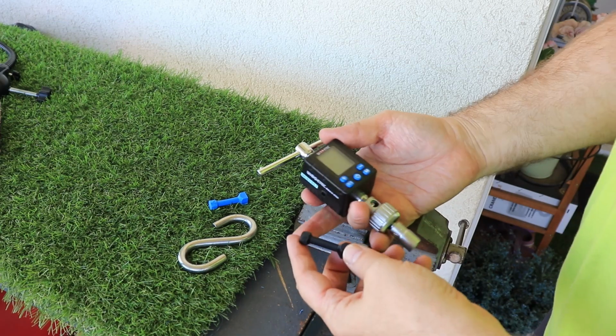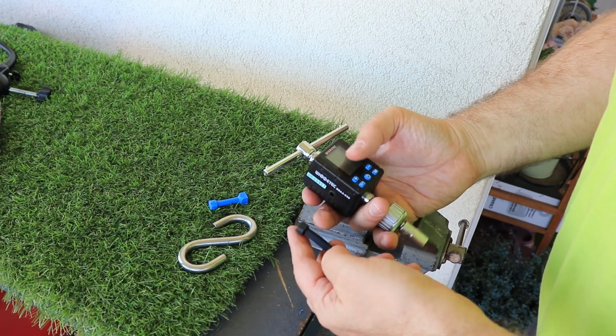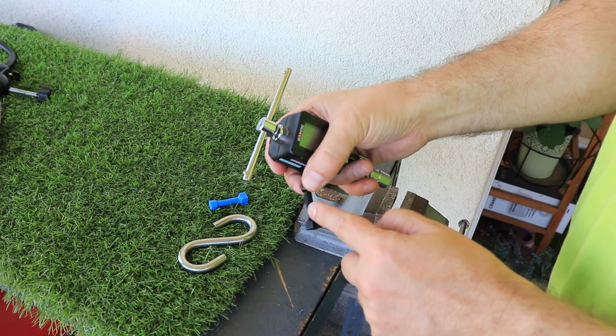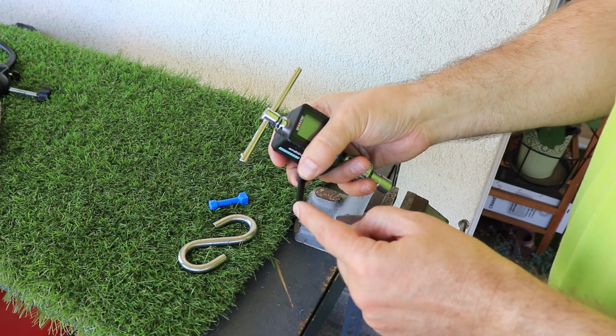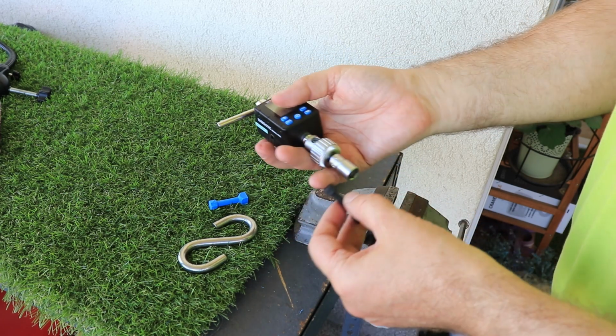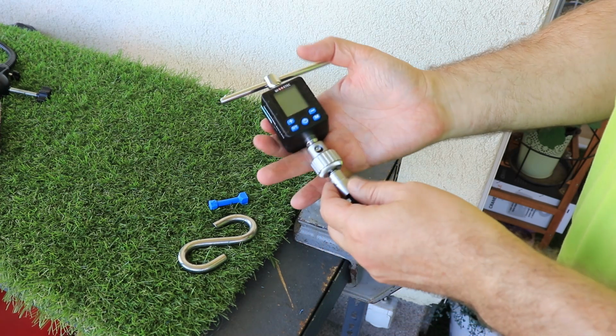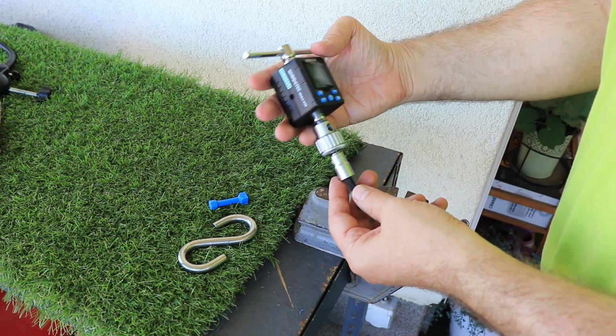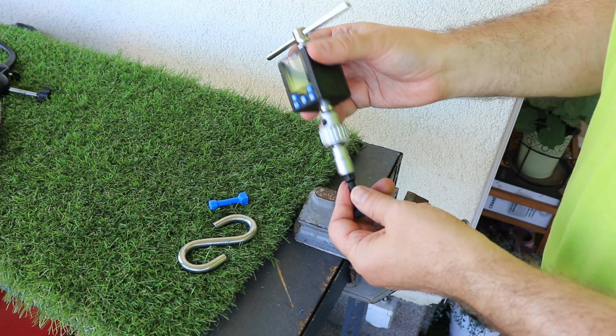And now torque or twist test. Usually I get very similar results like with the bending test. I have these test objects 6 mm in diameter. This side goes into the vise and this side goes into the digital torque meter. And I want to record the load at 90-degree angle and the maximal load.